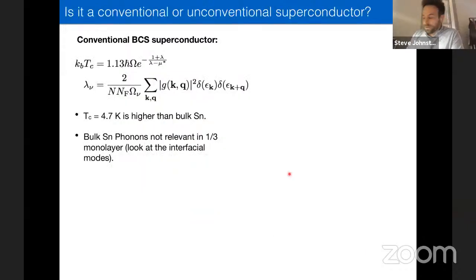Okay. So, the first thing we wanted to rule out was the BCS mechanism. We wanted to make sure this wasn't an electron-phonon mediated superconductor. As you probably all know, Tc in BCS theory goes like the characteristic phonon frequency multiplied by e to the minus (1 plus lambda) over (lambda minus mu star). Mu star is a measure of the Coulomb potential. Lambda is a dimensionless measure of the electron-phonon coupling, which you can think of as just a Fermi surface average of the electron-phonon vertex.